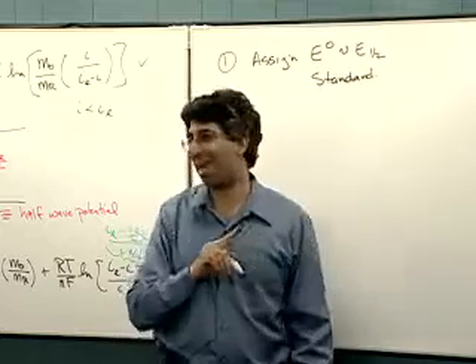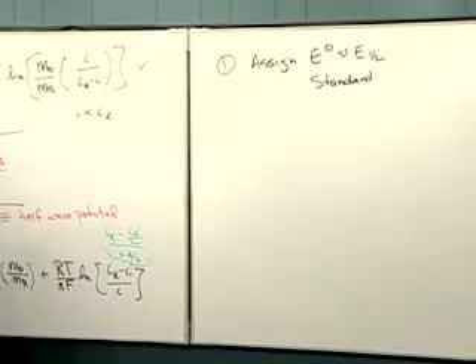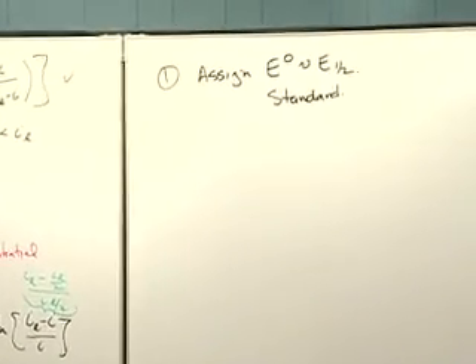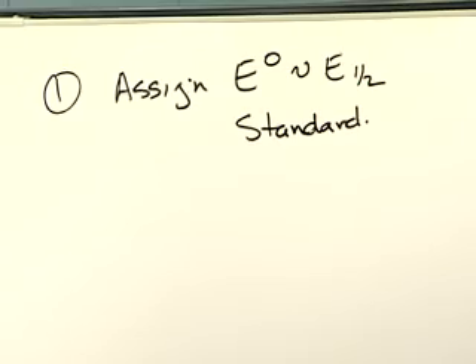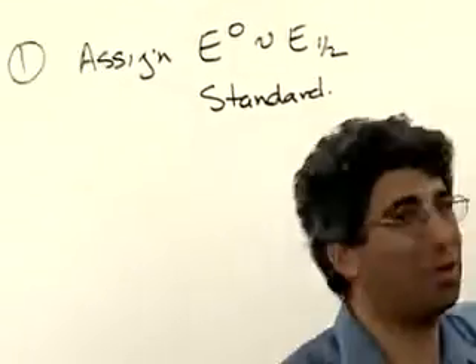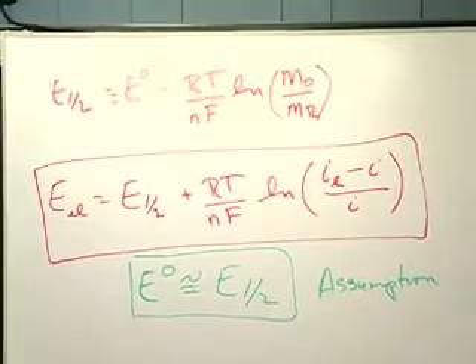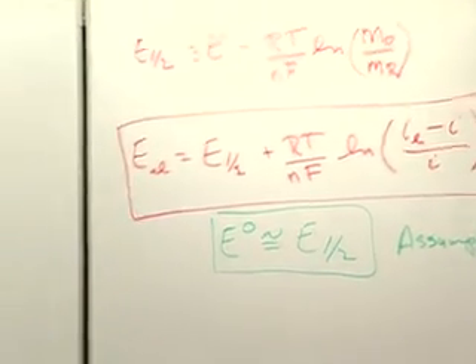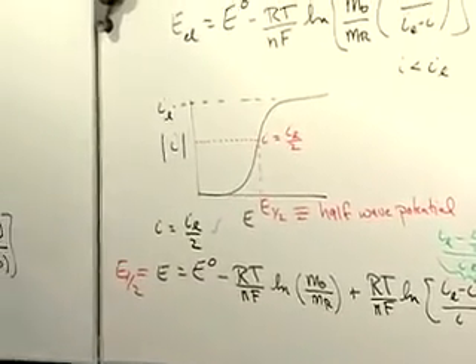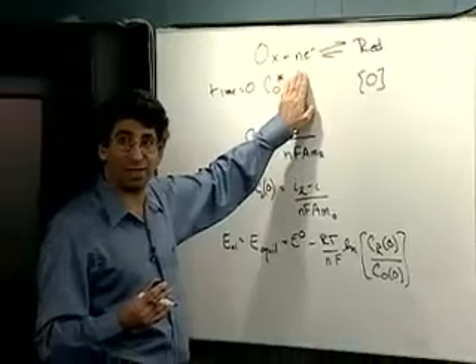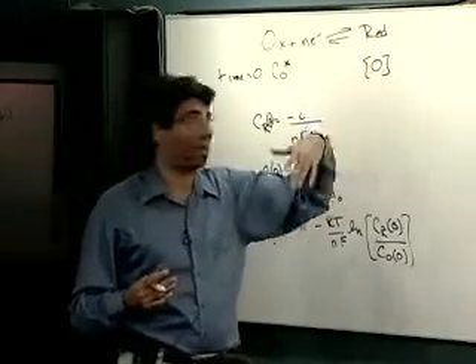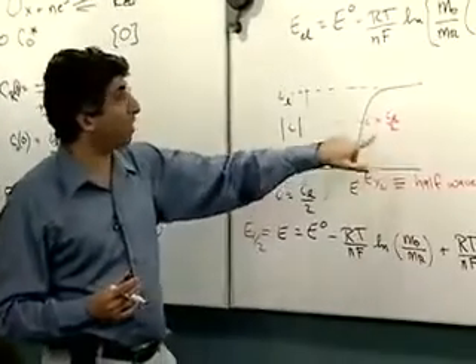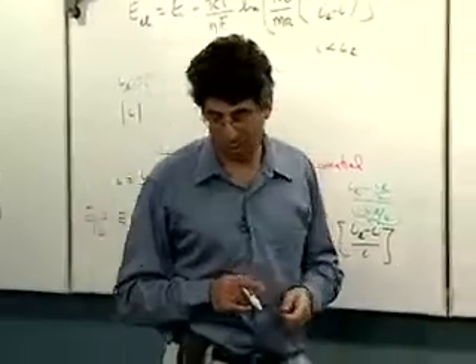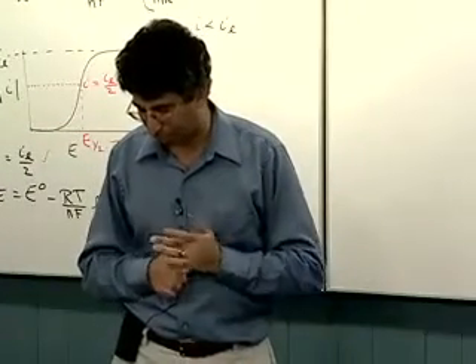That is, the number I am getting out of this experiment is the redox potential when I have 1 molar concentrations of oxidized and reduced present, and when I have 1 atmosphere of pressure, and when I have room temperature. Now, I'll point out to you all these equations, even though I write T here, actually assume room temperature. So you have to put in the 298 degrees Kelvin that goes with that to make that statement true. But the interesting thing is that I didn't put those concentrations or pressures into the cell. In fact, I have a cell sitting there that has a lot more oxidized than reduced in it, and whatever the pressure is. And yet, the value I'm getting out is the standard value under standard conditions. So it's directly comparable to what I would read off of the table.